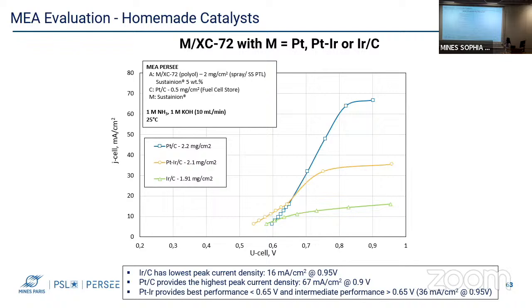Single iridium on carbon provided very poor performance toward the ammonia oxidation reaction with a peak current density of 16 milliampere per centimeter square at 0.95 volt. Platinum on carbon produced the highest current density with a peak of 67 milliampere per centimeter square at 0.9 volt. Platinum iridium was more advantageous in the low potential region. However, its peak current density lied between that of platinum and iridium.